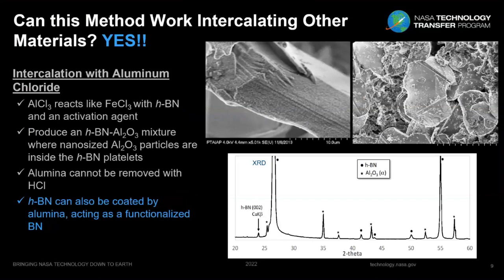Can this method work intercalating other materials? Yes, we can intercalate other materials. Here I'm demonstrating the intercalation of aluminum chloride. Why aluminum chloride? It reacts very similarly to iron chloride with hBN and using an activation agent. You have to use that activation agent. It produces alumina, which we are not able to remove, and that's exactly what we want when we add aluminum chloride. In this case, the alumina acts as a functionalization of the hexagonal boron nitride.